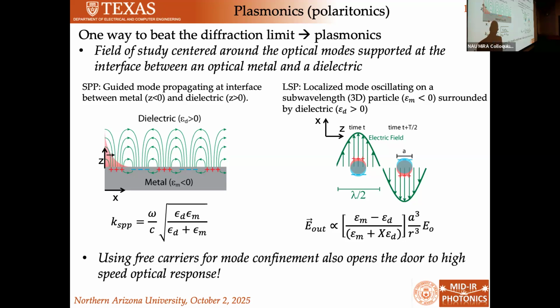When I say an optical metal, what I'm talking about is a material whose permittivity is negative, right? This is the way that we're going to define metals in the optical regime. So in this case, this is a surface plasmon polariton. Polariton means it's this hybrid excitation. Surface means that it's at the surface of our optical metal. And so this is a mode that propagates along the surface of the optical metal, consisting of a charge oscillation, or a plasma, in your metal, and then this electromagnetic wave that is tied to that charge excitation on its surface.